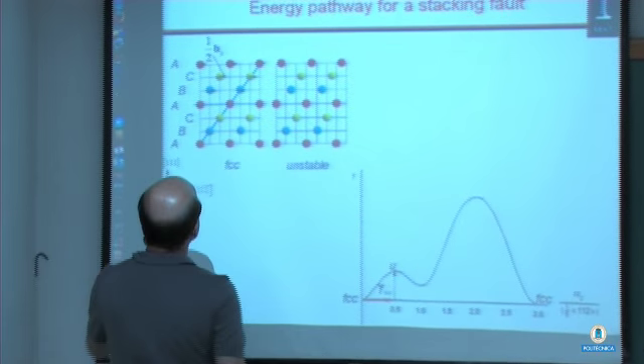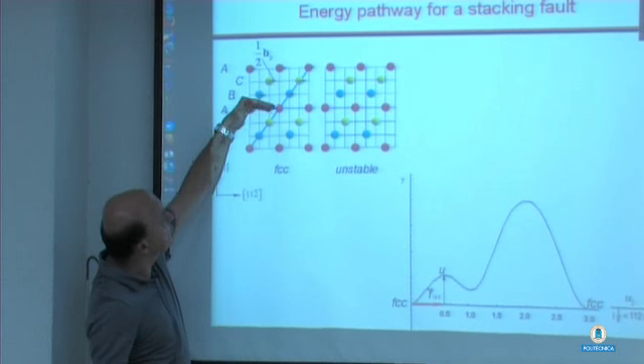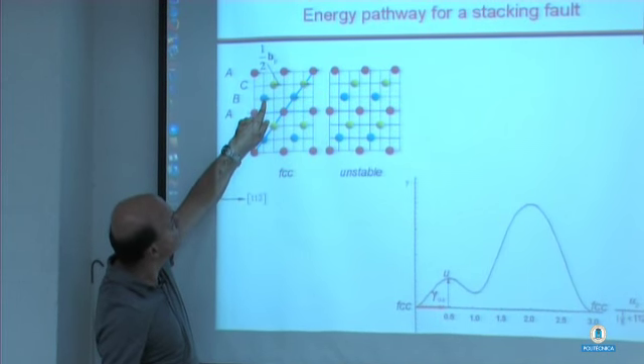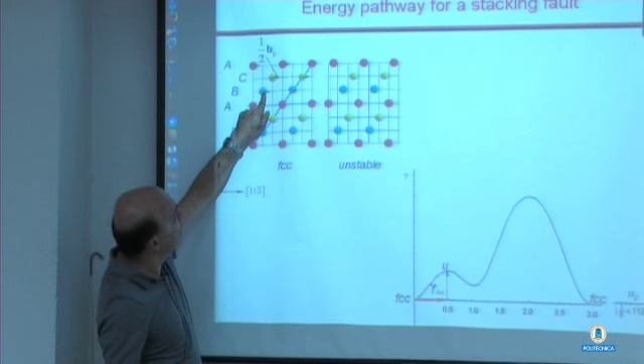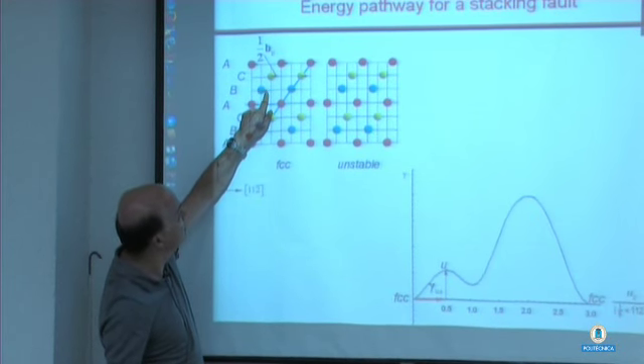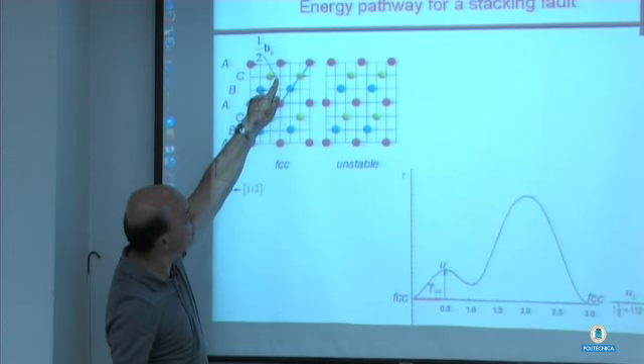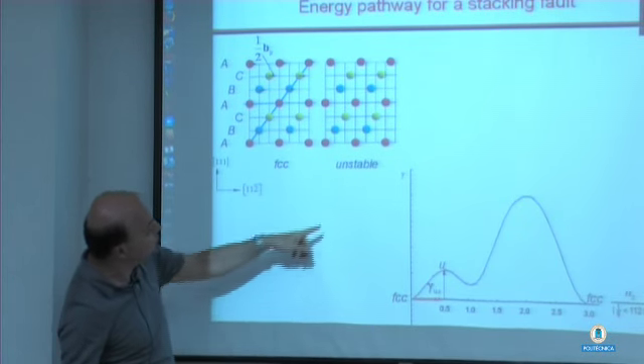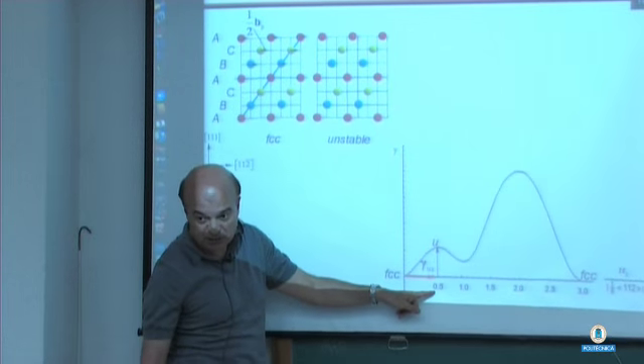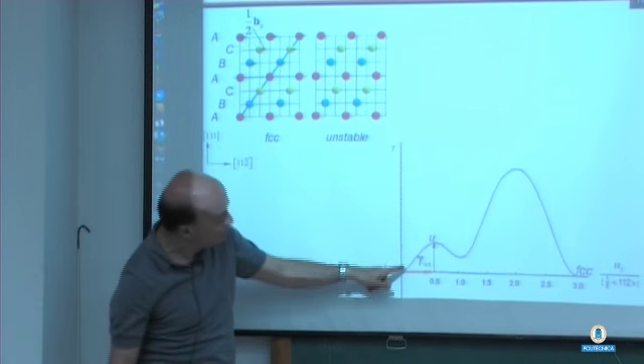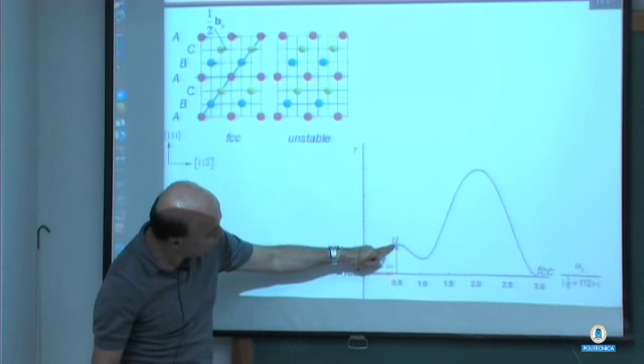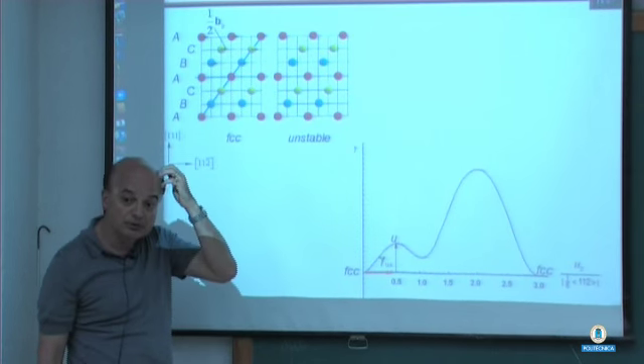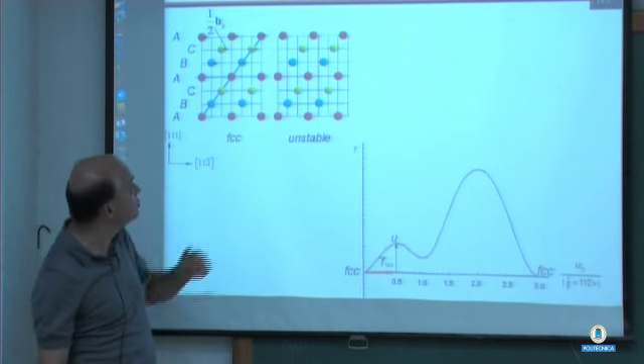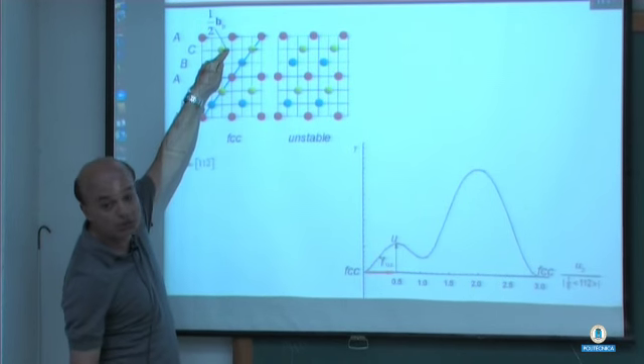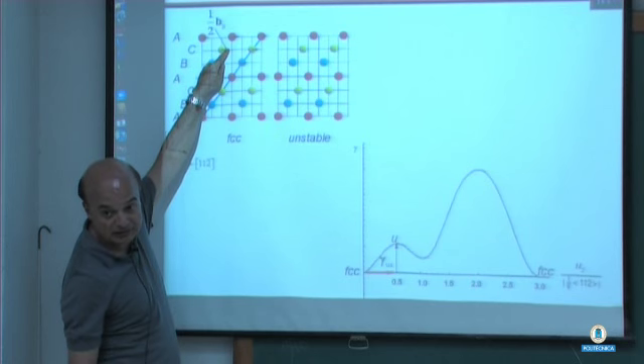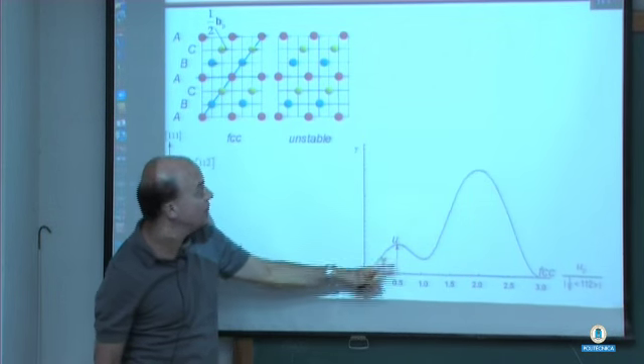Okay, and let's say this is your slip plane, and if you move the blue atom by half a Burger's vector from left to the right, okay, and then move the green one also, if you plot the energy versus displacement in the 1, 1, 2 direction, you reach a peak that's called the unstable stacking fault energy. So that position is an unstable position. It doesn't want to stay there, and it requires energy to get up that far.